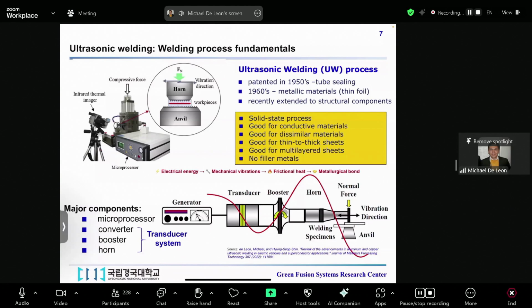So the basic process of ultrasonic welding is illustrated here. The workpieces, or overlap samples, are placed on an anvil, as shown here. Then the horn moves down, and a normal force is applied perpendicular to the plane of the weld interface. The normal force helps the horn and the anvil maintain contact with the workpieces and hold them together.